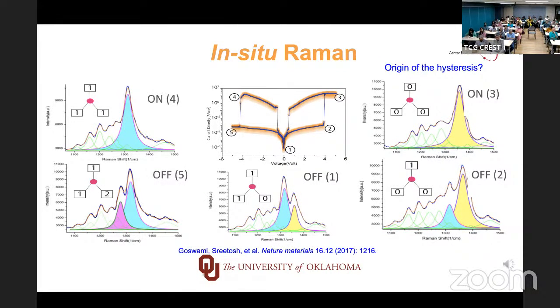What you notice, interestingly, is that all these off states have at least one ligand not in the equivalent state, whereas in the on state, all the ligands are in the same state. And that tells you exactly what the mechanism of switching is.